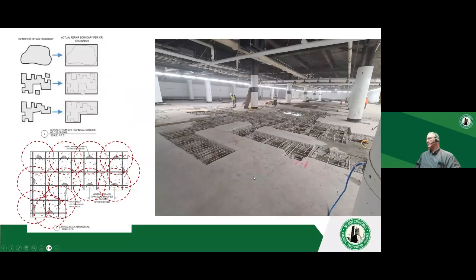Now, if you do regular conventional reinforcing, this is a pan joist system where we're removing the concrete, doing the regular concrete repair, and you put galvanic anodes in around the perimeter. This is a targeted application. You want to make sure you set up your repair areas so that they're not going to produce additional cracking. So this is from the ICCP technical guideline. And then you put the anodes in.